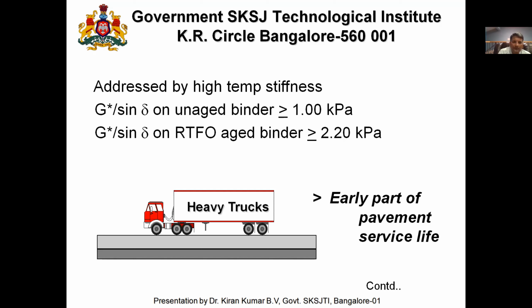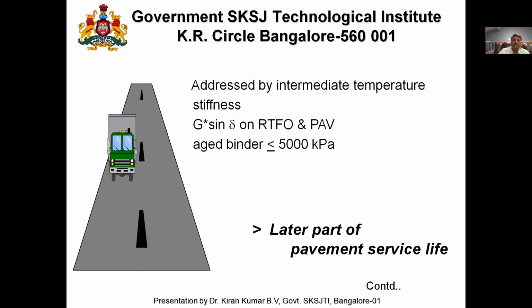So these complex values which I was talking about, the G star sine delta for unaged binder and aged binder, are given here. The minimum value should be greater than this. Then after aging, meaning during the service period and in the later stages once the service period is over, again we have the values of G star sine delta, after aging through RTFOT and PAV, whatever the value is coming, whether it is falling within this range of 5000 kPa. So all these things have to be determined before finalizing.